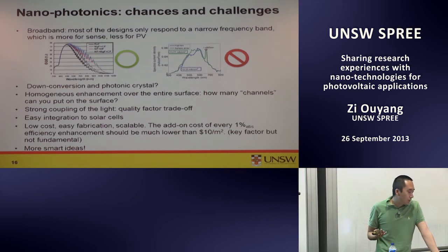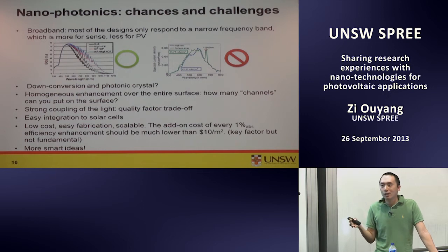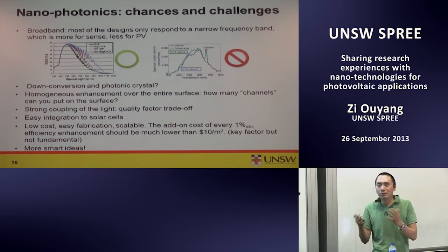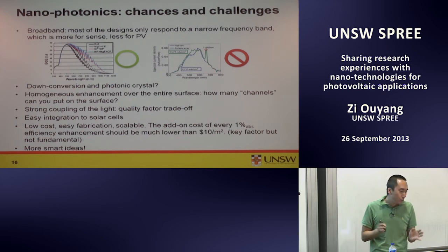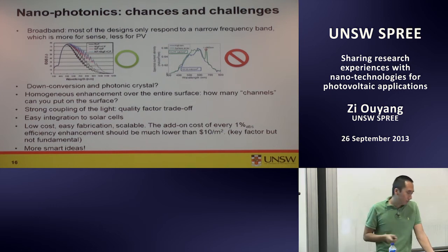How many channels can you put on a surface? One interesting thing is, okay, you want to have multiple channels, you want to have a broadband absorption. Why don't we just throw different nanoparticles with different sizes and see what's happening? But the problem is one nanoparticle physically occupies a space. So if at this location you have a boost for 900 nanometers, you actually lose the ability to boost 600 nanometers. So if you integrate all together, you actually won't get any broadband enhancement peak like this.